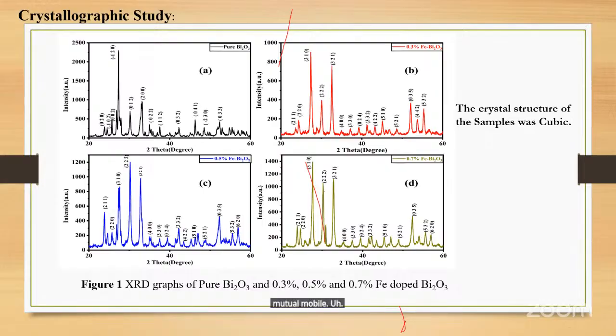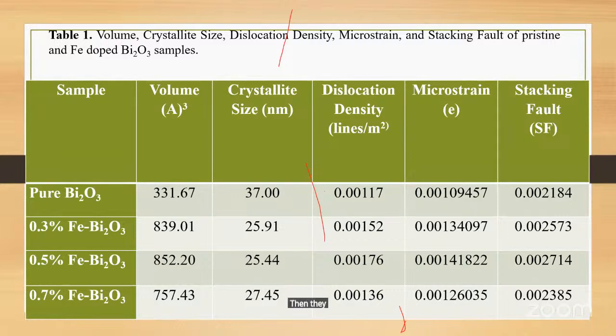Now you see, these are the XRD pattern, and from this we can calculate the lattice parameters. Okay, lattice parameters. These are the lattice parameters, and we have calculated the volume of the cell, crystallite size, dislocation density in lines per square meter, microstrain, and stacking faults.